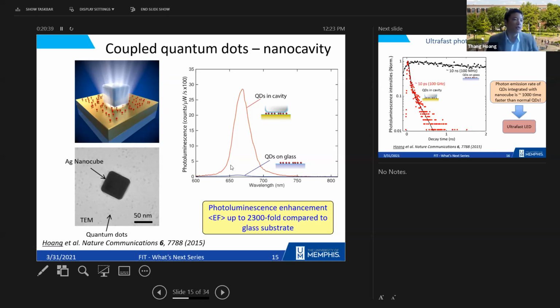And here on the right, you can see the light emission. This measures the intensity of light as a function of the wavelength. We see that the quantum dots underneath the nanocube are very enhanced, very strong compared to the quantum dots on the glass. So you see that they are much stronger. In the best case, we can get more than a 2,000 times enhancement in the photons emitted by the quantum dot underneath the nanocube compared to the quantum dot on the glass without the nanocube. So they are much more intense when they are coupled to this nanocube, which is enhanced by the surface plasmon,